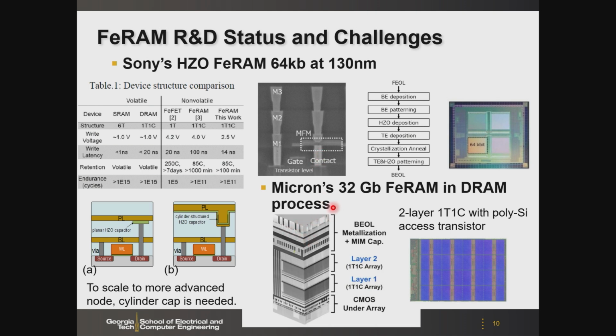And then if you look at Micron's recent announcement from the last IEDM, they reported 32 gigabit FeRAM. So they're using the DRAM process. Micron is a memory vendor, so they have a specialized DRAM process. But in this case, they integrate 2-layer 1T1C with polysilicon as the access transistor. This is because for the ferro, you don't need ultra low leakage, right? Unlike the DRAM, where you need a specialized DRAM transistor. But for ferro, it's non-volatile memory, so they can use polysilicon with a higher leakage current. Then you can do this 3D integration with 2-layer 1T1C at the back end of the line. So those are the amazing announcements from the community recently.